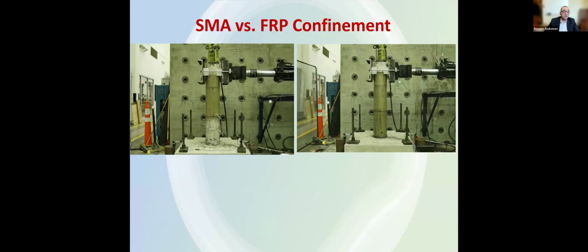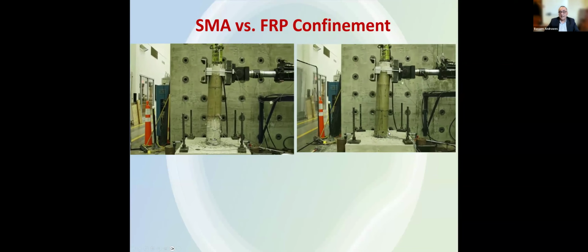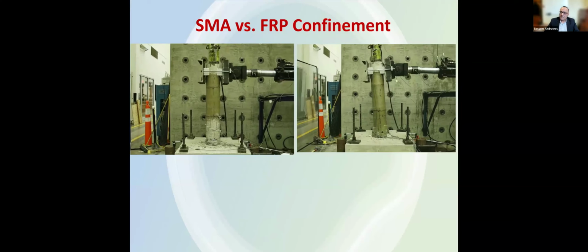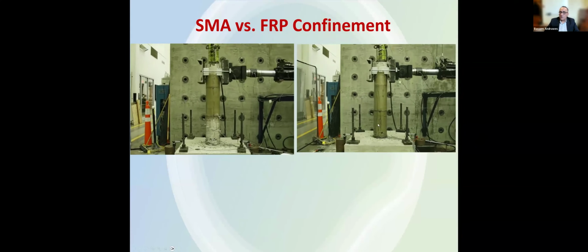We have two columns, the one on the left wrapped with the SMA spiral, again, active confinement, the one on the right, passive confinement with glass fiber reinforced polymer. The FRP started well at the beginning. However, we started seeing early compression failures, crushing essentially of the concrete, and then what looks like an explosion at the plastic hinge of the columns.